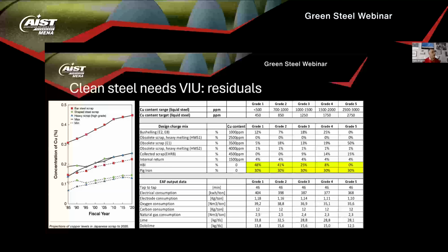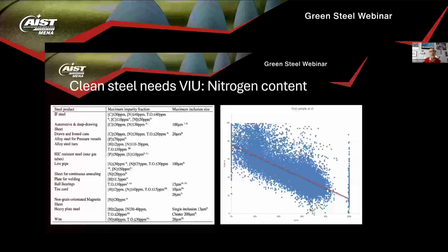Also Arvedi, even though they don't produce interstitial free nor electric steel, uses a significant quantity of HBI and other virgin iron units to close the balance with an acceptable content of copper and tramp elements. And there is also another side effect. Mr. Koppel properly mentioned the content of nitrogen. The content of nitrogen is critical for some steel grades, for instance, as I mentioned, interstitial free for exposed body parts and electric steel. First and foremost, scrap brings in nitrogen. The study on the right comes from one of our plants. You see a very solid trend of decrease of the nitrogen content with the increase of the virgin iron units. The graph is executed between 0% DRI and 80% plus DRI.